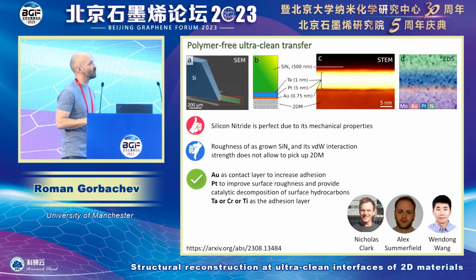And so what we've been working on in the last 4 years, maybe even 5, is trying to transition away from polymers. And the system we chose was silicon nitride. Silicon nitride membranes are extremely mechanically strong. Now, before the 2D materials, it was one of the strongest thin layers you can ever make. And they have wafer scale growth, so potentially scalable, but they don't stick to 2D materials. So how do you go about that?